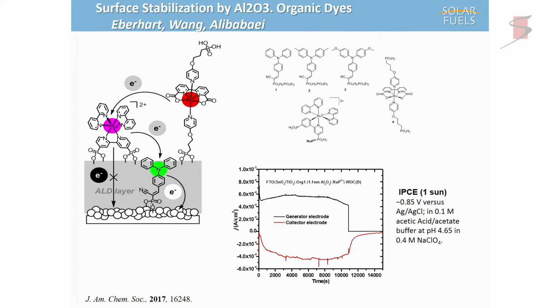It sits there. If you put these molecules, or organic molecules, you put them on the surface this way, in aqueous solution, and did an oxidation, they would quickly decompose. What we've done now is to bury it in Al2O3. The molecules are stable in this environment. But on top of that, then I've got another reagent. This is just an electron transfer mediator.